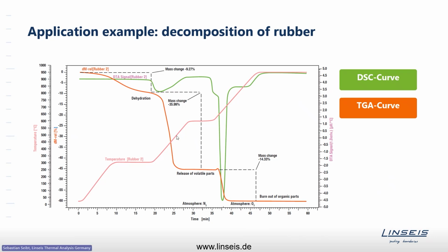Then the sample was heated up to roughly 700 degrees Celsius. During that heating segment, there was a huge mass change and a simultaneous huge reaction peak, which symbolizes the pyrolysis of this rubber sample. And finally, the atmosphere at this point was switched from nitrogen to oxygen, and then the heating was again performed up to 1000 degrees Celsius.